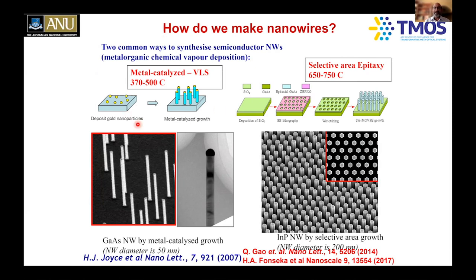So in the case of this VLS growth process, we use metal nanoparticles, gold nanoparticles, for example, as small as 10 nanometers up to as big as 300 nanometers. I'm giving an example of nanoparticles of about 50 nanometers in diameter. Gold has a very high melting temperature, more than 1,000 degrees Celsius. But once gold reacts with gallium or aluminum or indium, the alloy melting temperature comes down to as small as 350 degrees Celsius.